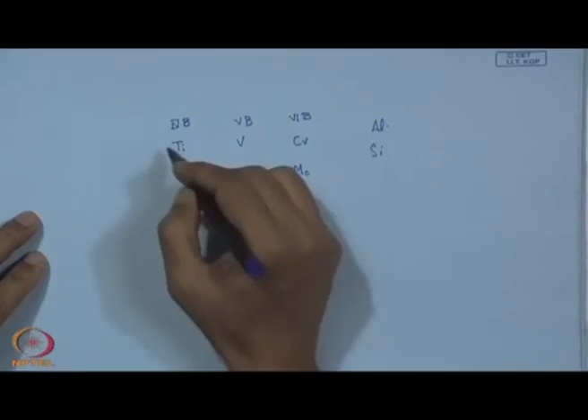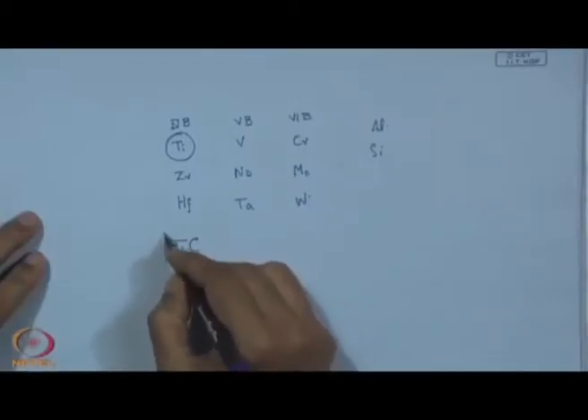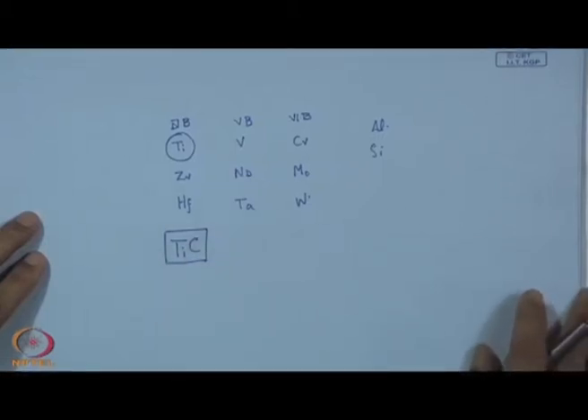Now, here we find that titanium is so popular and so important in that titanium carbide has had tremendous success in offering such kind of property, particularly in all forming tools or tools of production, just like forming tool or cutting tool, and this TiC at the top of the tool works so successfully that it can raise the lifetime of the tool by a few times, or even the cutting speed can be increased quite substantially. Now, this TiC is indeed an effective solution to those problems where the wear on the tool becomes a great problem and a challenge.